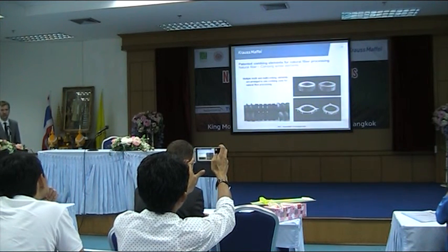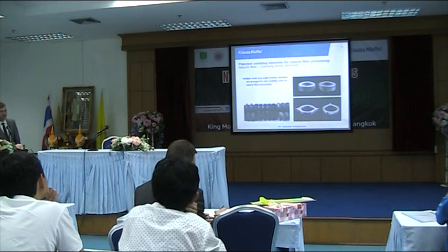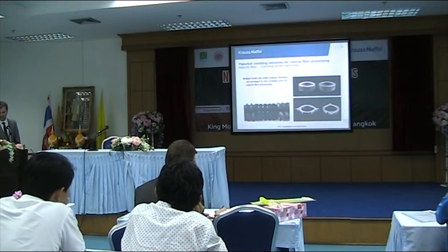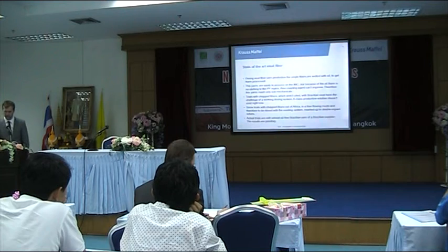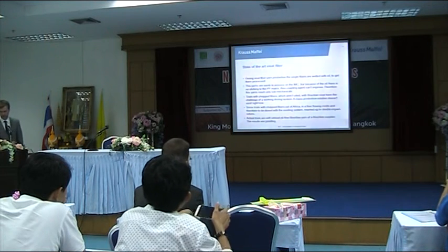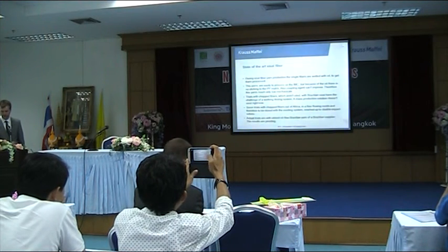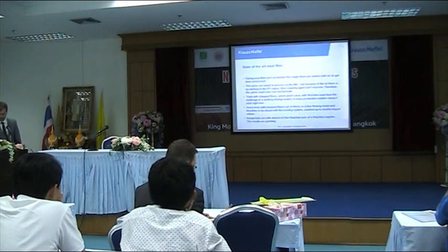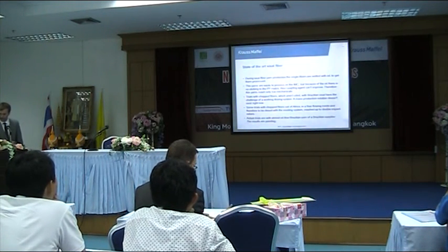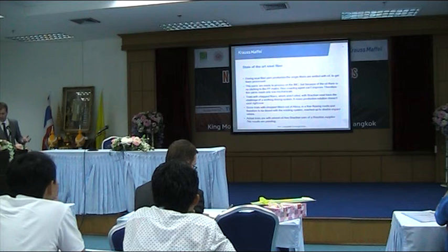So there is already several expertise in processing natural fibers. This was also one slide concerning processing sisal fibers. During sisal fiber yarn production, the single fibers are wetted with oil to get them processed, and now these yarns are easy to process on the IMC.